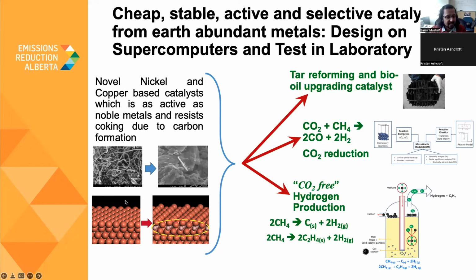And here you can see an example on the left-hand side. At the bottom, you can see nickel here and the modified nickel in that yellow oval, which we predicted and developed using supercomputing facilities and quantum mechanical simulations. And later, when we looked at the experiments on the left, you see this picture where the catalyst is covered by all these carbon fibers, whereas the modified catalyst remains clean. And where do we apply these novel catalysts for different reactions? A few of them are listed here.